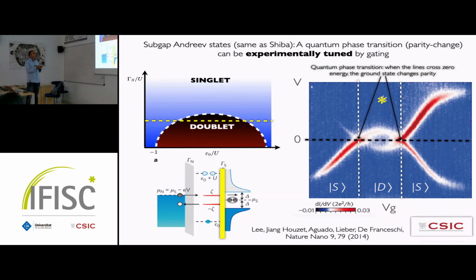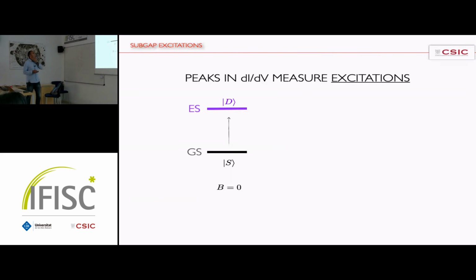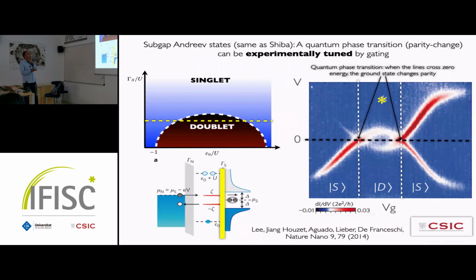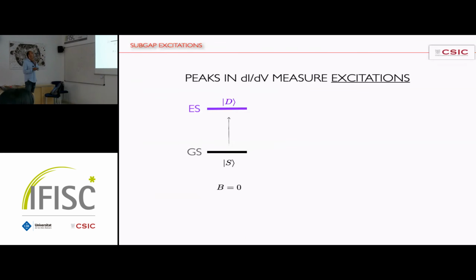And now you enter into this loop here, which is essentially this phase here. This is the doublet, and then you are back to the singlet. Here the line cannot be seen, but you are back in the singlet. So these loops or eyes in dI/dV are a signature of this doublet phase in the quantum dot coupled to the superconductor. All right, now you have to remember that these peaks are actually excitations on top of the ground state, okay? So if I am in a singlet, my peak is a doublet excitation, okay?